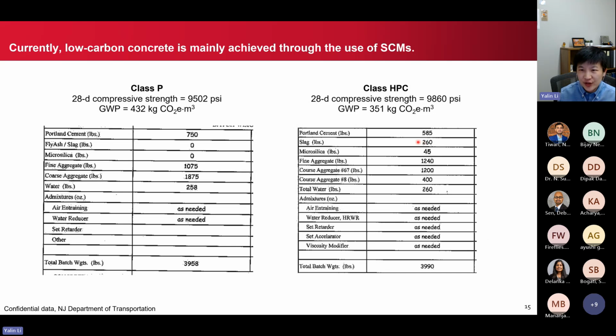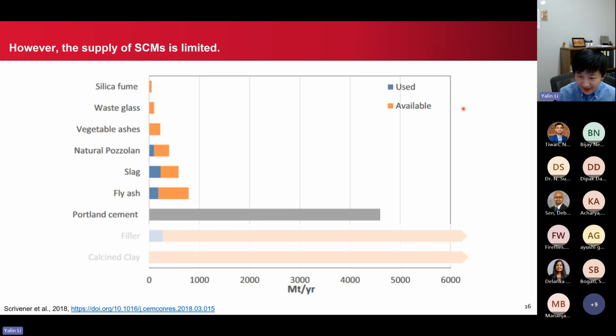So these changes here essentially lead to the reduction in the greenhouse gas emissions. So that all sounds nice, but if we look at how much of these supplementary cementitious materials we have versus how much of the cement we use, you will quickly realize that the amount of SCM materials is not sufficient to meet our demands.